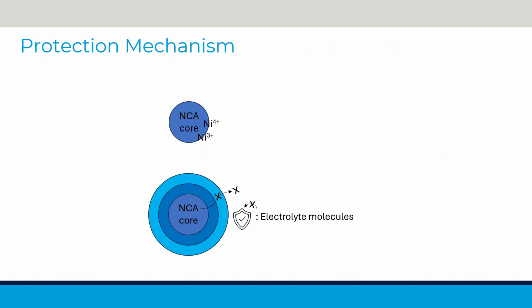Intuitively, this illustrates how these layers contribute to mitigating nickel dissolution. At high charge, surface nickel exists mainly as unstable nickel 3+ or 4+. When not protected, some electrolyte species attack the surface. The surface nickel 3+ or 4+ is reduced to nickel 2+ with gas formation. The 2+ dissolves into the electrolyte, leaving defects and weakening the cathode surface.